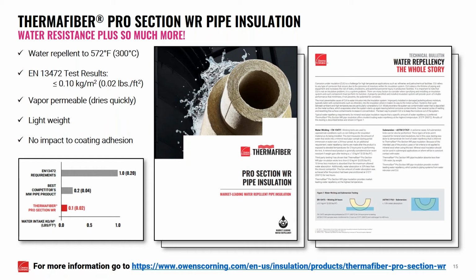The point is that we have water repellency to 572 degrees Fahrenheit, which is the best in class and highest temperature water repellency in the market. It also has the lowest amount of water wicking into the product in the marketplace. So if you see that plot down below, you can see those requirements of 1 kilogram per square meter that we talked about earlier. And then you see the next closest competitor, and then finally our product at the bottom, you can see it's significantly lower. And again, because mineral wool is vapor permeable, it will dry quickly if it gets wet.